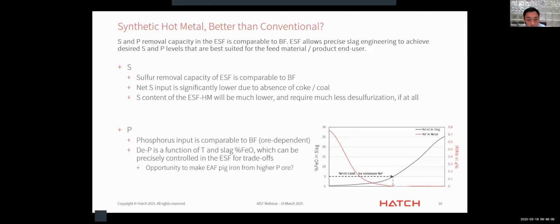Phosphorus is similar. The removal capacity is comparable to the blast furnace, and it's highly dependent on the ore selection. And well, dephosphorization is a very strong function of both temperature and slag property. Since we can control those parameters very precisely, it provides a lot of opportunities to enhance phosphorus removal through optimizing both the slag and the process.